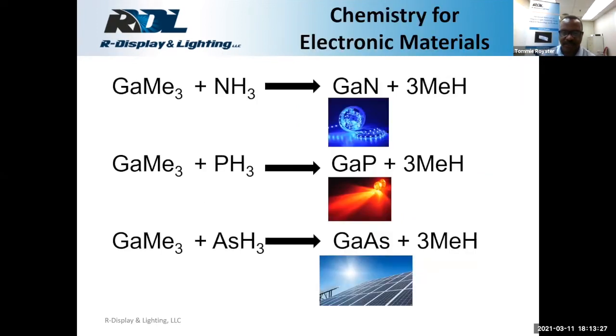Chemistry for electronic materials is very important, and these materials play an important role in our everyday lives, even if we don't realize it. Shown here are the reactions involved in what is called metalorganic chemical vapor deposition processes. This chemistry involves using transition group 3 organometallic materials with group 5 compounds to form group 3,5 semiconductors. The first reaction shown here, reacting trimethylgallium with ammonia, gives us the elimination of methane, forming gallium nitride, which is a high band gap material.